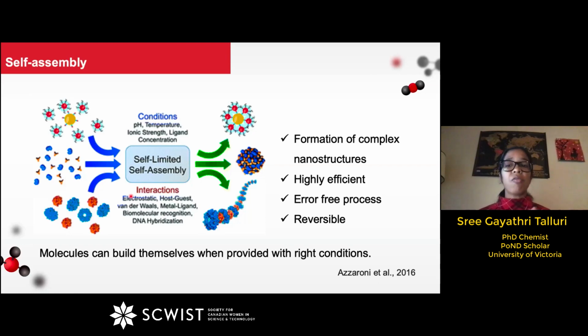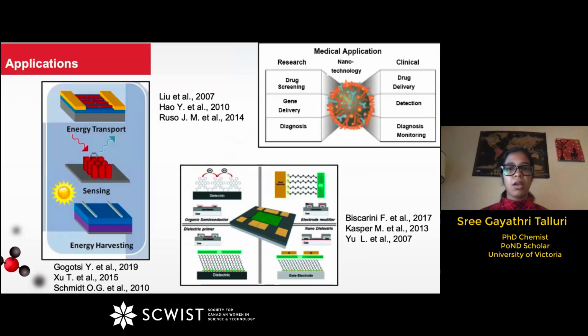Unlike molecules formed by chemical bonds, the structures formed by self-assembly are held together by weak physical interactions. Because the molecules are held together by weak physical interactions, they tend to be reversible. The reversible nature of self-assembly allows components to adjust their position once they are formed, leading to more efficient and error-free process. This is exactly the process that we are looking for to build nanostructures.